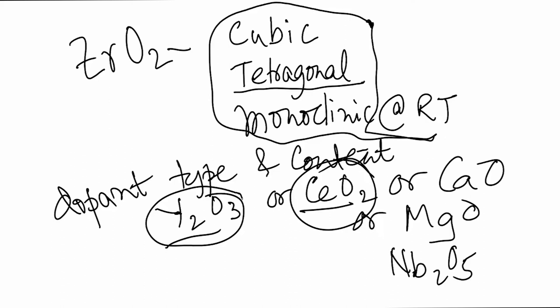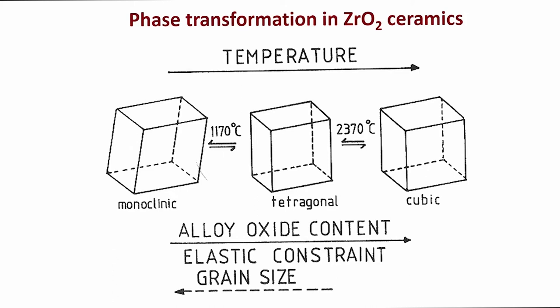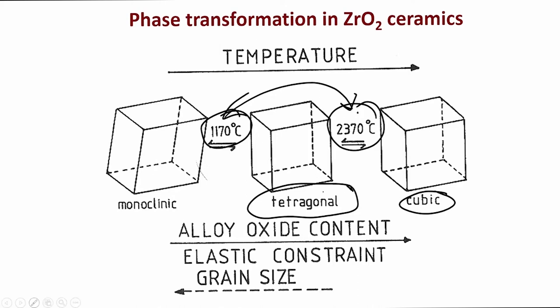So, there is a compositional effect, and because of this compositional effect, the thermodynamic property of the system also changes, and that allows the tetragonal phase to be retained at room temperature. This is one of the important things that one should remember. Now, as far as the typical phase transformation temperature is concerned, the cubic phase is stable above 2370 degrees Celsius. Between 1170 and 2370, it is the tetragonal phase which is stable, and below 1170 degrees Celsius up to room temperature, it is the monoclinic phase which is stable. So, these are the three major polymorphs of zirconia.